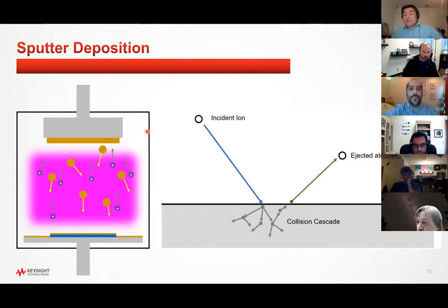And so the process that we use to put down that seed layer, it's called sputter deposition, and this is what I worked with. And the idea is essentially you're in a vacuum chamber and you put your sample on a table and you have a target of the material that you want to deposit. And you flow in some gas and you generate a plasma. And the plasma is oriented in such a way that the positive ions of the gas are going to collide with the target. And so you have an ion that comes in.